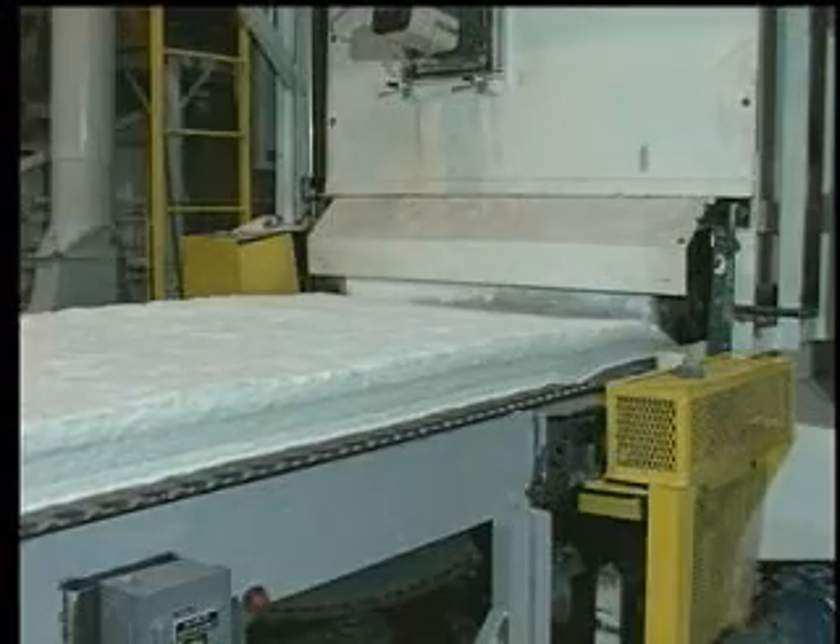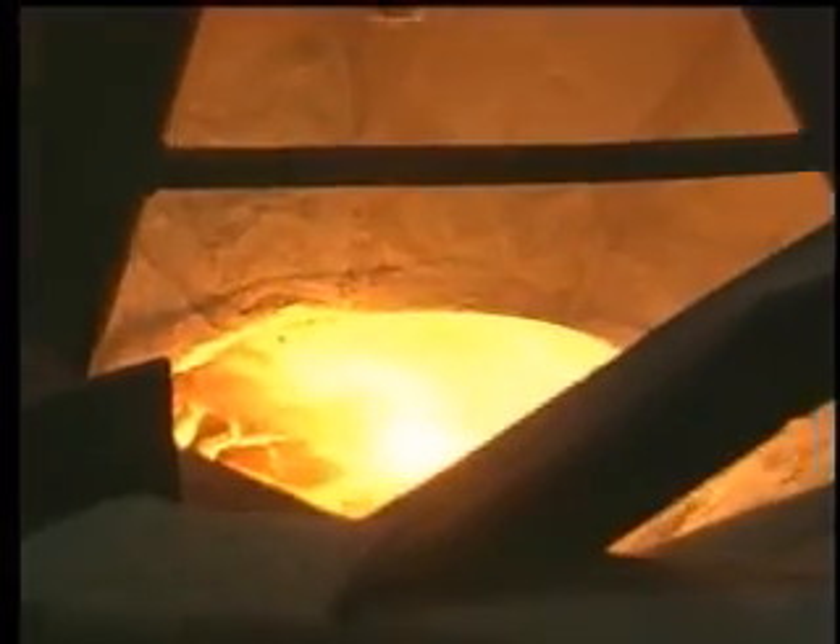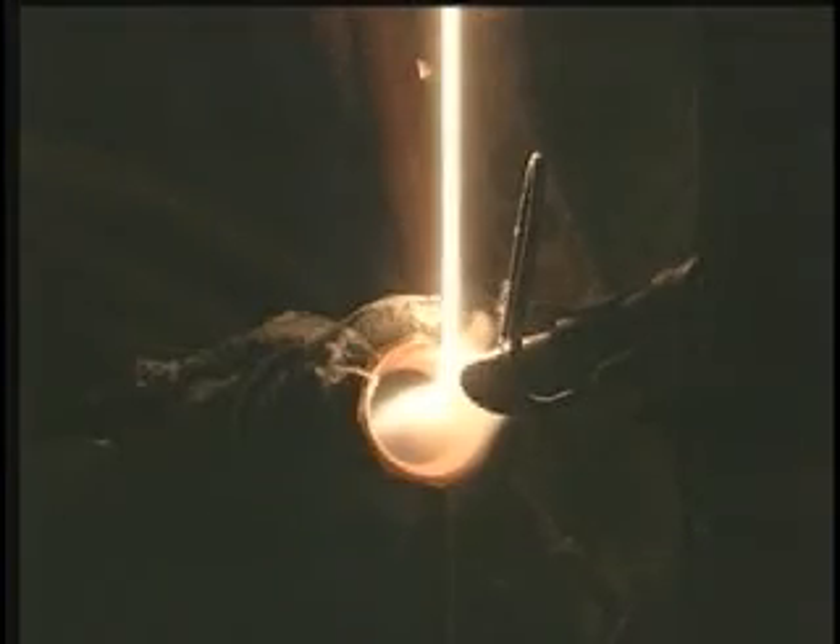The first results in our Kaowool blanket, which we make by melting kaolin clay at more than 3,400 degrees Fahrenheit. The melt stream is then blown tangentially, or at an angle, by high-pressure air, which solidifies it into strands of fiber.